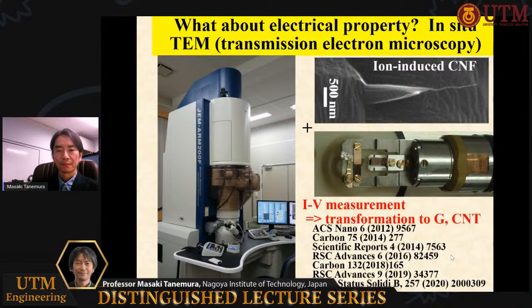What about the electrical property? Of course, we can measure the electrical property in the scanning electron microscope, previously used for the measurement of mechanical properties. But crystalline structure change induced by the electron current flow will be interesting. So we installed a special sample holder in the transmission electron microscope system to measure the electrical property. And we observed the transformation from amorphous carbon to graphene and amorphous carbon to carbon nanotubes. Today, I will show you some examples.